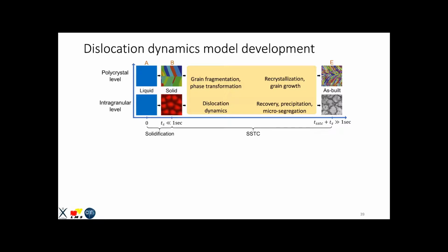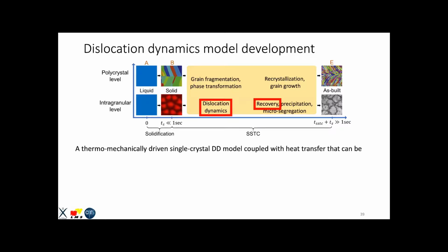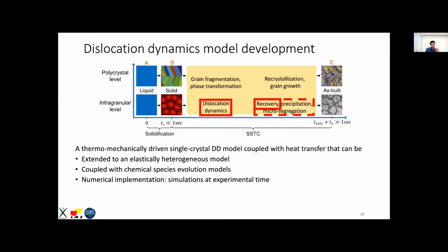Okay, what do we want the dislocation dynamics model to do? Well, it is a single crystal model right now. And we want it to be driven by thermomechanical driving forces such that it can predict temperature changes as well as dislocation dynamics and their coupling. Next, we want this model to be able to extend to elastically heterogeneous domains so we can study dislocation interactions with grain boundaries. We want the model to be coupled with chemical species evolution, for instance, phase field modeling to study precipitate evolution. And we want to numerically implement it so that we can run simulations at experimental timescales.